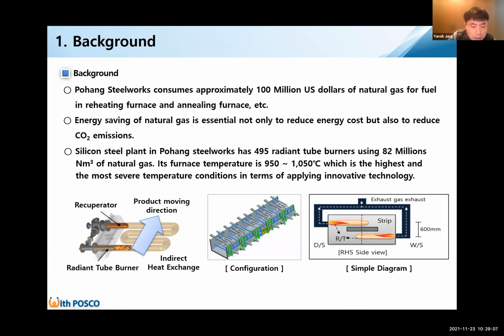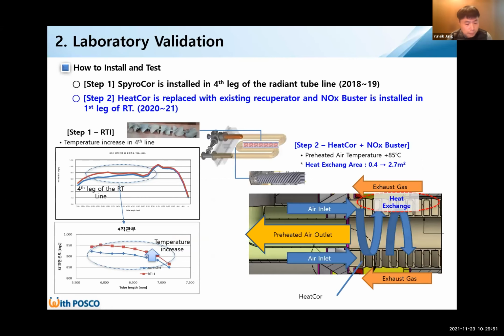The silicon steel plant in Pohang Steelworks has 495 radiant tube burners using 82 million normal cubic meters of natural gas. Its furnace temperature is 950 to 1050 Celsius degrees, which is the highest and most severe temperature condition in terms of applying innovative technology. We chose the most severe conditions for experimental and field circumstances to prove energy savings and robustness. I will explain how we installed and tested.